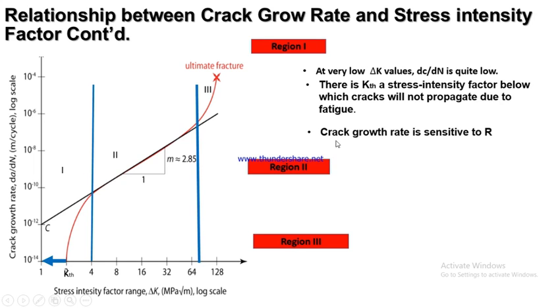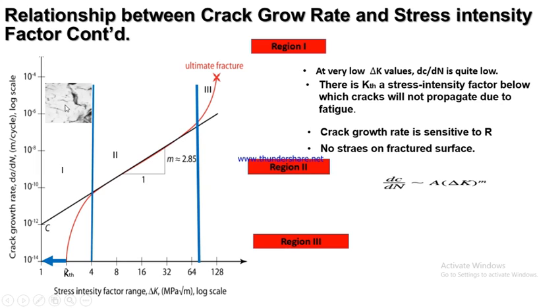Another thing we're supposed to understand is that the crack growth rate is sensitive to what? To the stress ratio of the material at this stage 1. The crack growth rate is very sensitive to the stress ratio. Then at this particular point, you will not see striation on the fracture surface of the material, especially at this place where the crack initiated, which is region 1 of the crack growth rate.